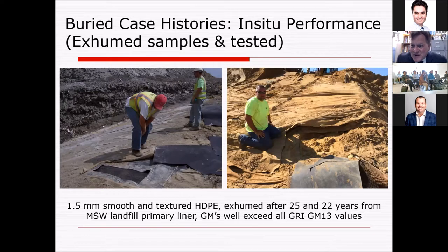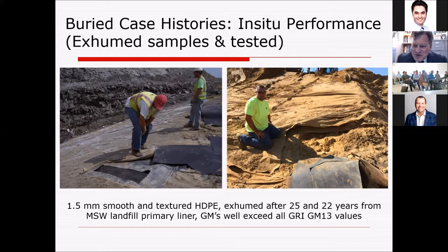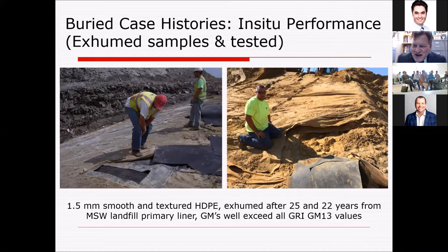I've made a living of digging up landfills — there are many papers on this. These are two cases of 1.5 millimeter both smooth and textured geomembranes after 25 years of being exposed to leachate in a municipal solid waste facility — the geomembranes behaved excellently. These are not very fancy formulations, they're bare-bones formulations. Standard OIT was fine for the analysis and the membranes were working great.